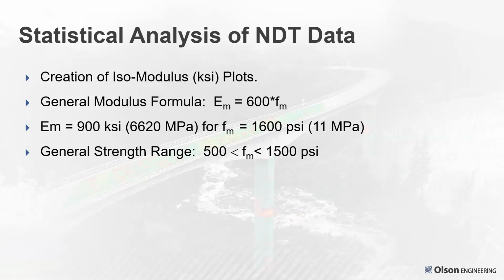And then he applied some Italian research on old brick structures that related modulus to strength of the masonry. So this is using a low strain modulus to predict a relative strength at best. From that, if you had a Young's modulus of 900 KSI, kips per square inch, that corresponded to a masonry strength of 1600 PSI. So the general, very approximately estimated strength range was 500 to 1500 PSI.